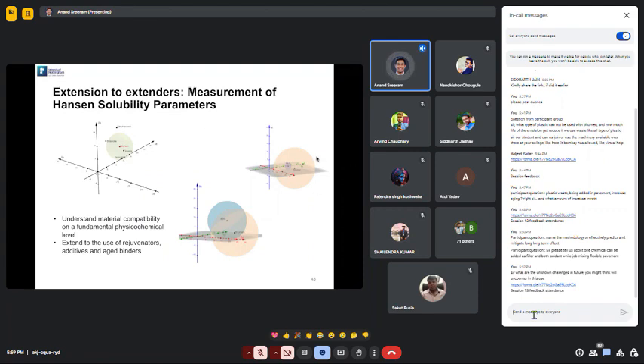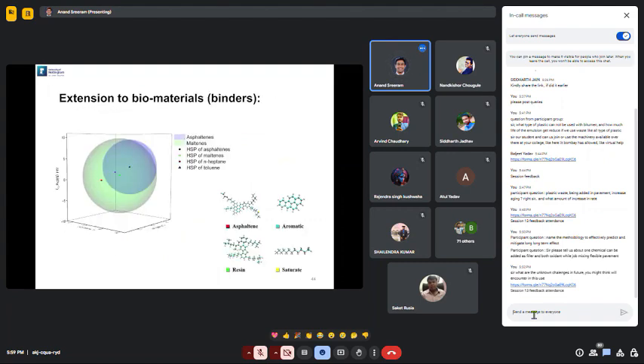Whereas if we add other kinds of additives, for example, it's very common to add different kinds of plastics into bitumen. You can see although the solubility sphere of the plastic is inside bitumen, it's very small, and it doesn't really have affinity to bitumen, and that's why a lot of the performance properties of bitumen may be compromised if we add different kinds of plastics, in terms of increased hardening, which will most likely lead to significantly deteriorated performance in terms of fatigue and low temperature cracking, and so on. So we've used it as a fundamental metric to see what kinds of materials we can add and not add to bitumen. Recently we also extended this to different kinds of biomaterials.